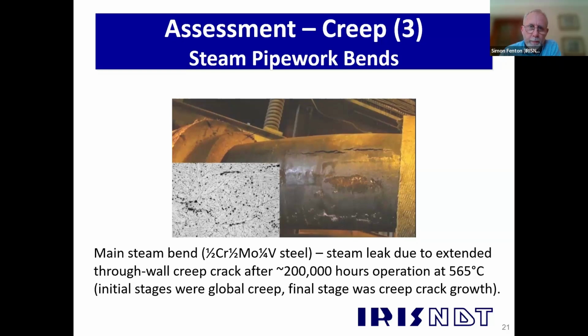And in this particular example, the creep crack that you can see on the outside actually started as global creep through the body of the component. The component was 65 millimeters thick. But in the latter stages, it grew very rapidly by a process of creep crack growth. So this is creep damage sweeping away at the crack tip and forming a very rapid progression of the creep crack.